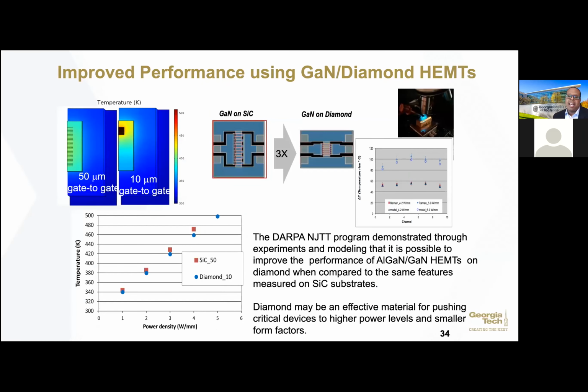So why move to GaN on diamond? As I mentioned before, GaN on diamond gives you this high thermal conductivity material that should be great for dissipating heat. Here's a device that we modeled. This is GaN on silicon carbide. You can see each one of these channels that are spaced apart by 50 microns. I can actually place this on top of diamond according to my modeling and place these now only 10 microns apart. And what you end up getting is basically this device, the channels are no hotter than this one over here because the diamond helps with heat dissipation.